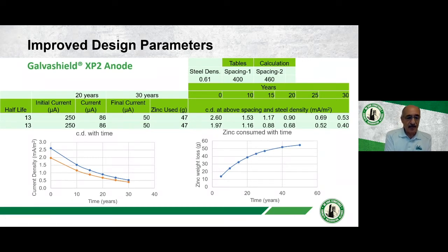But now let's turn the tables around and let's say, well, we got the details. What we need to do is we want to design a current density at 30 years. So we need to know what the current density will be at 30 years. We still want a current density of 0.4, which is cathodic prevention level, and I'm confident that if your chloride level at the beginning is less than 0.85, by the fact that you are producing current throughout the 30 years and you're increasing the alkalinity around the steel, and you're reducing the chloride because you're repelling it away, I'm happy that 0.4 will be an adequate current density.